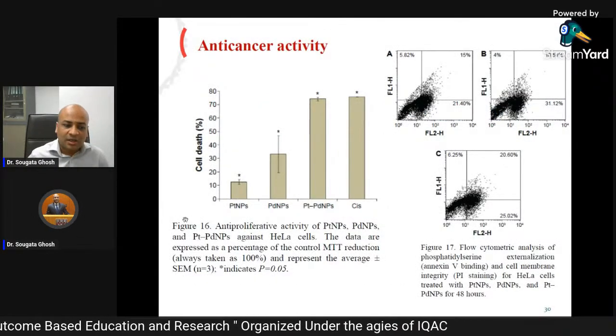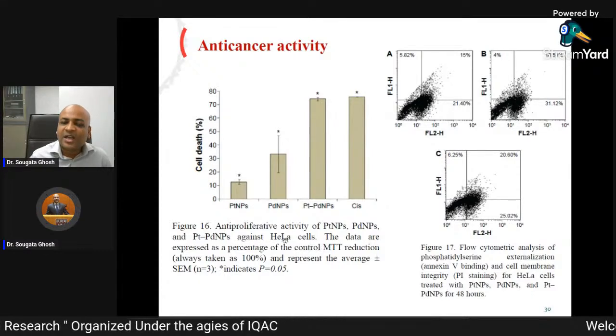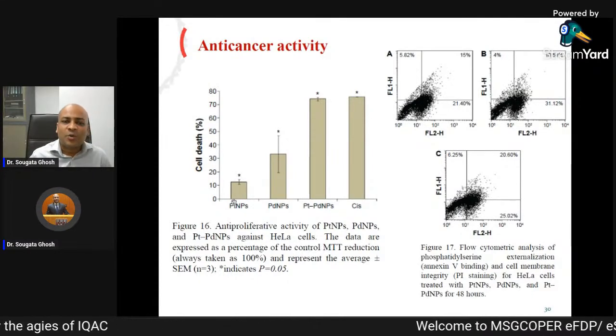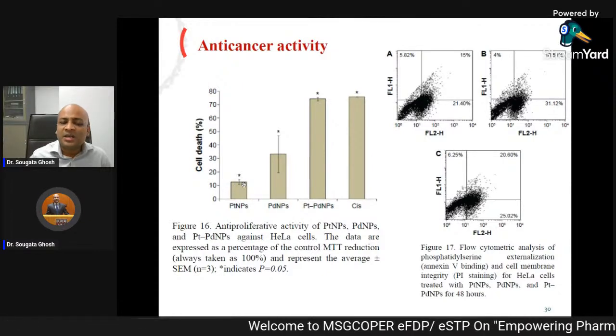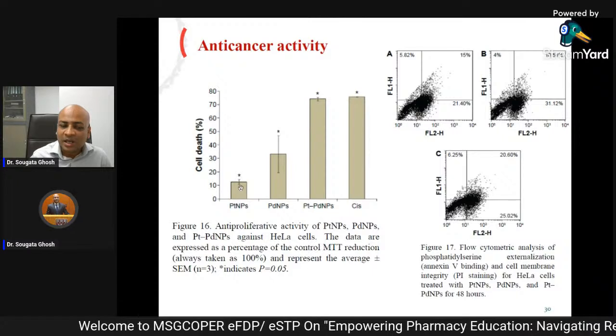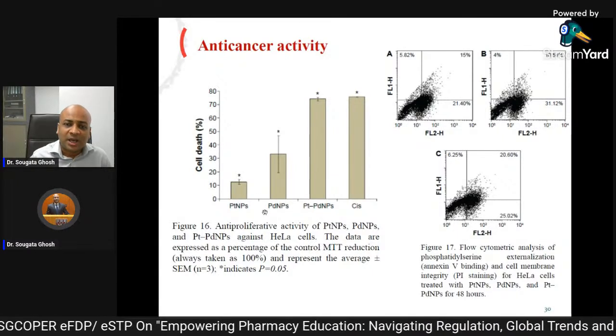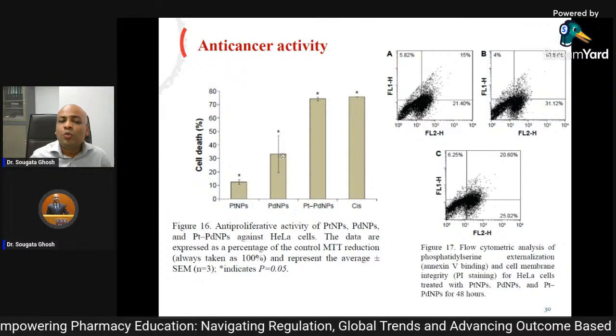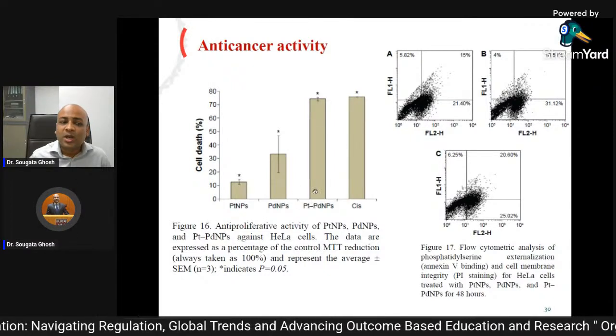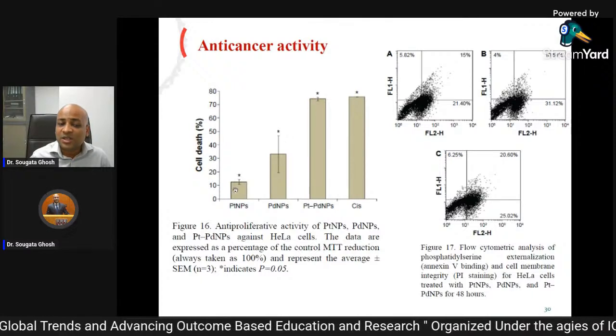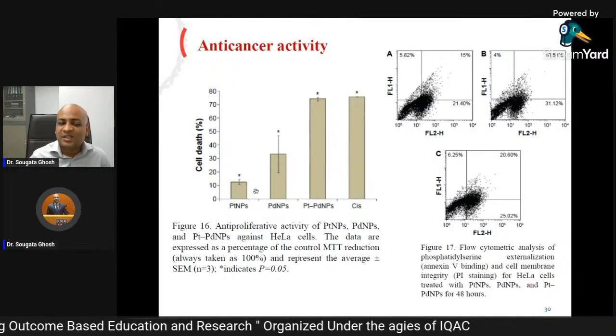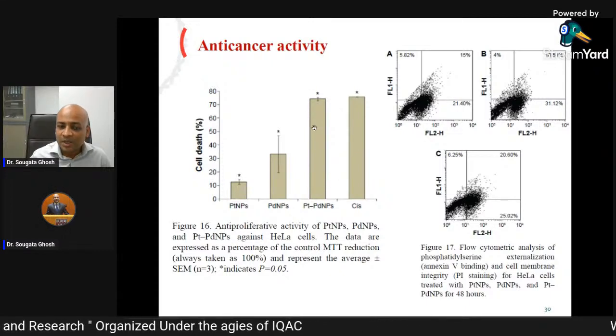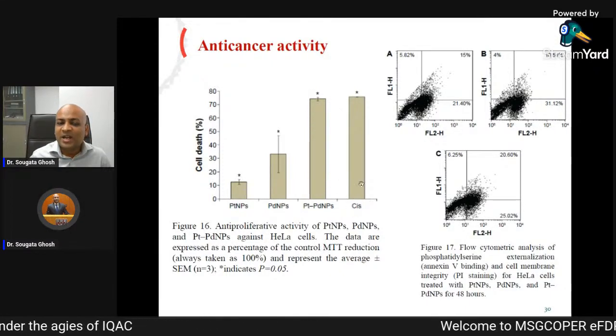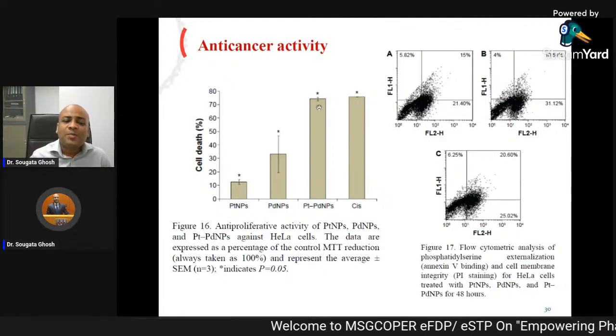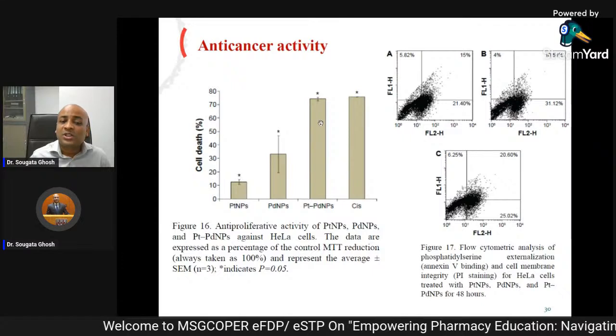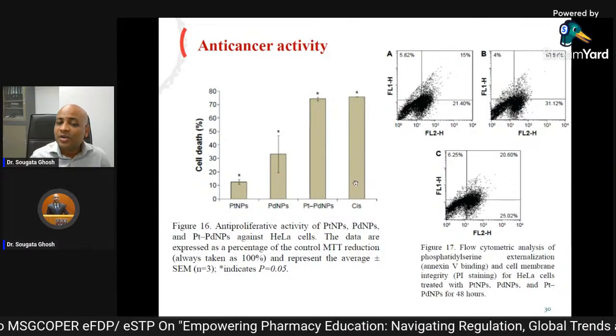Now, in case of anti-cancer, we used HeLa cell line, cervical cancer cell line. When we used platinum nanoparticle, there was around 15% cell death, HeLa cancer cell death. When we use palladium nanoparticle, here we could see around 32% cell death. When platinum palladium together, it is around 75%. You can see it increased. Platinum less, palladium less, but together it was very high. And we used a control standard drug cisplatin, it was also similar. So our platinum palladium bimetallic nanoparticle was able to show similar activity as the standard drug.